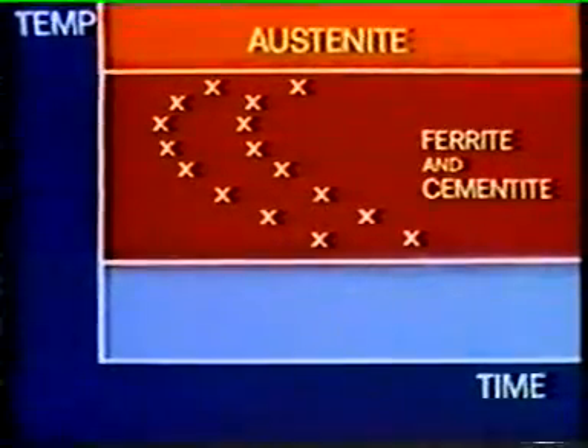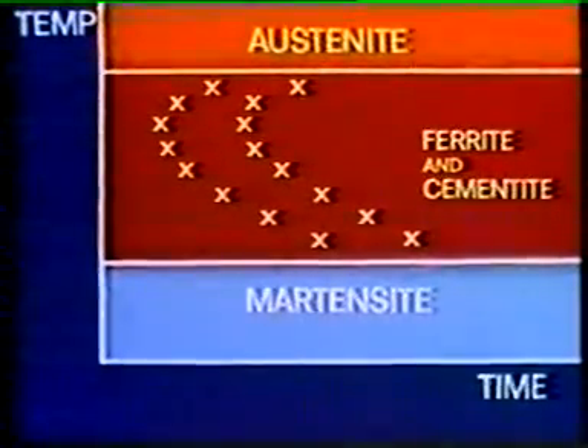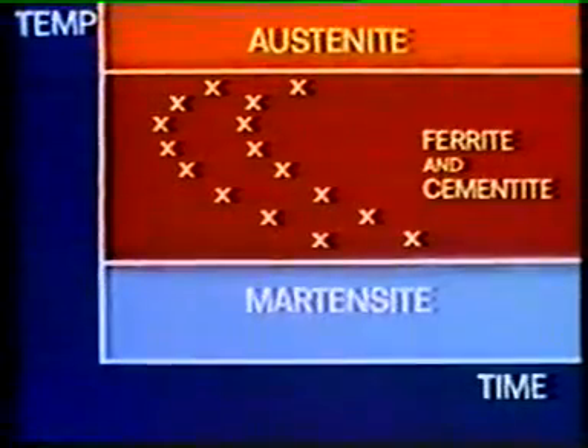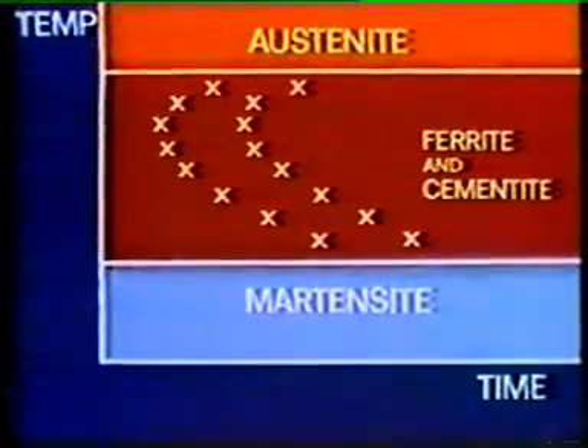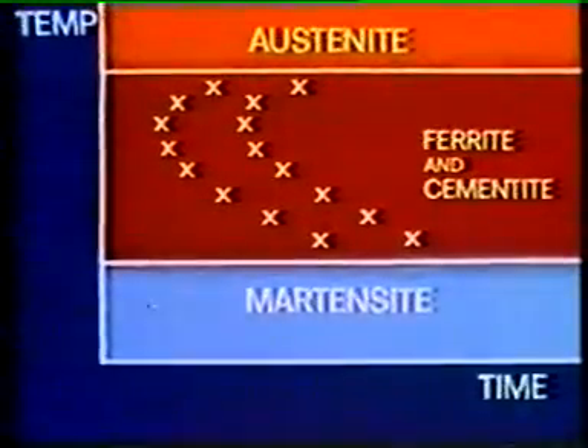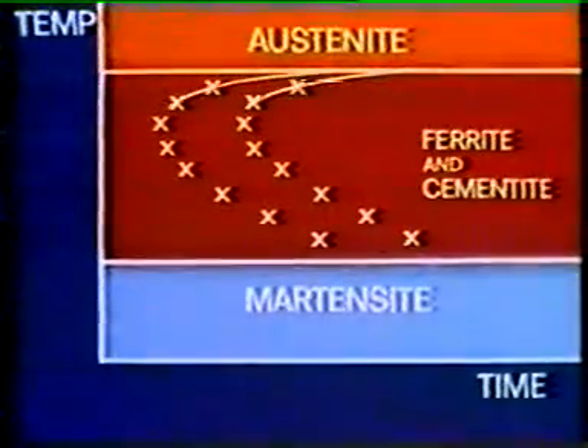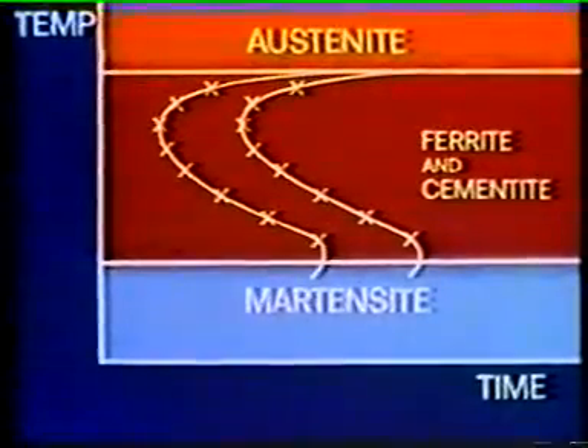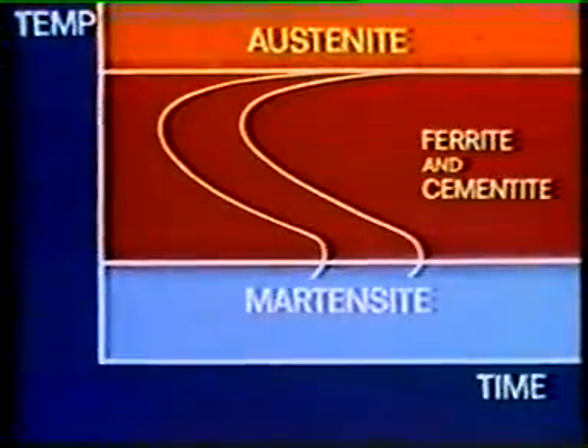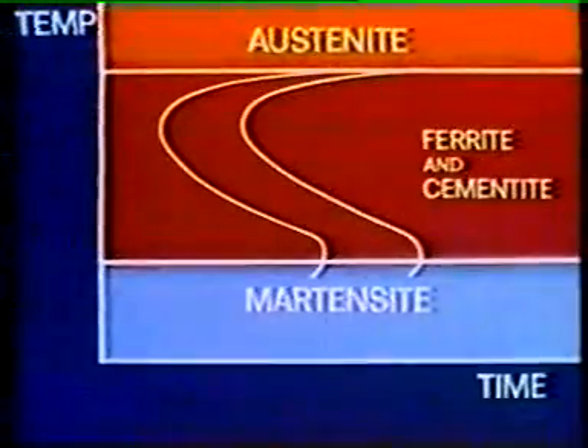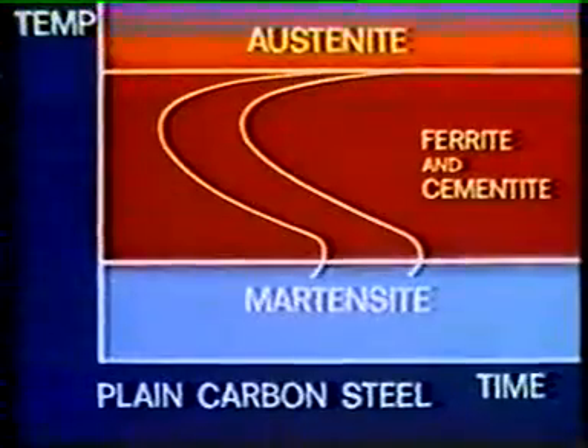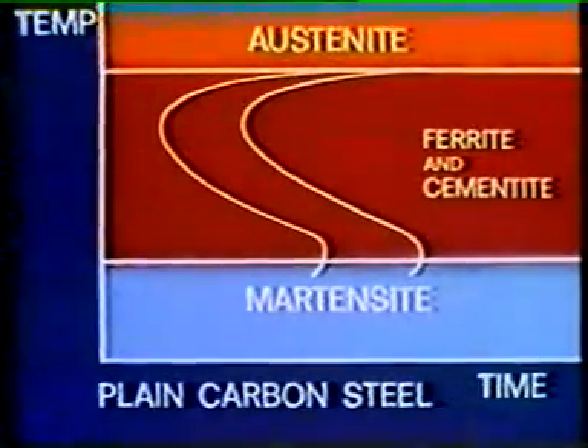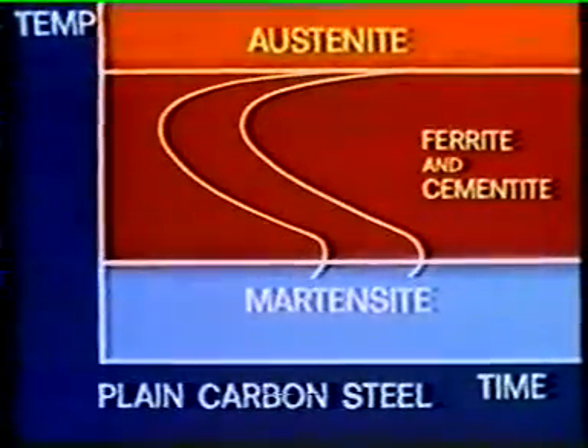This is done over and over again down the temperature scale till we reach the point at which the formation of martensite begins. After this point, the steel will harden, but only if it has not had time to transform at any higher temperature. By linking the points, we obtain time-temperature transformation curves for this plain carbon steel. Now let us plot the cooling rate of water on the same graph.